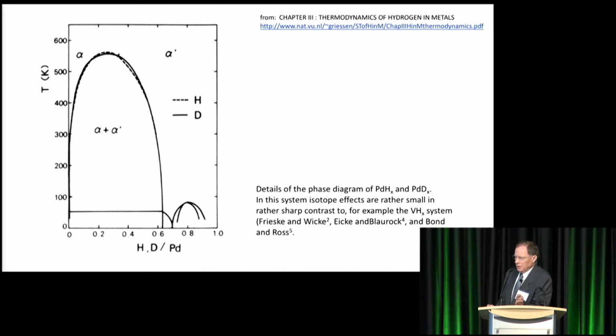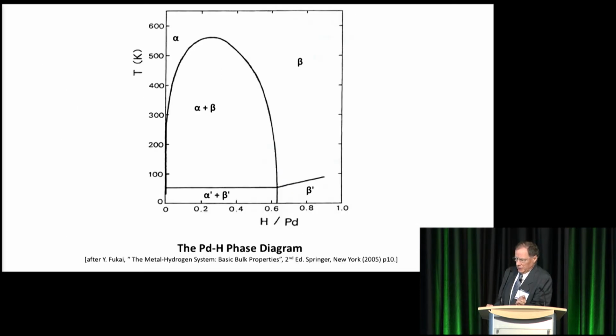In the palladium-hydrogen system, there has not been, at least to date, much evidence to support much of a difference between the isotopes. So I've taken the liberty of just dealing with them being the same in the phase diagram. This is a phase diagram, probably the best metastable one that we have to date, but what you'll notice in a minute is that all the equilibrium structures on the right are missing, because this is a metastable diagram with a minor mistake.